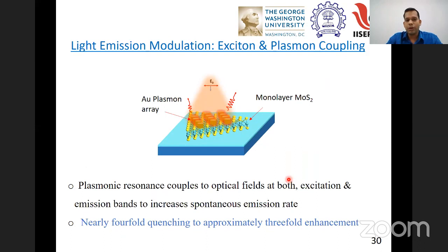And lastly, I will talk about another interesting topic which we are interested in. It is light emission and its modulation. Here we use monolayer MoS2 because it is a direct bandgap material and it gives luminescence at 680. We see that this luminescence we can tune further if we couple with a plasmonic array, and we can enhance it 3-fold or quench it 4-fold, so we can have tunability.